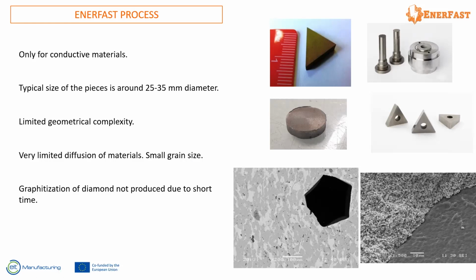And of course, there is no diffusion. The time is very short. It means that what you put in the die is what you will get after the end of the process. This is good for some materials and not so good for others. And also in the case of metal diamond tools, you can avoid graphitization of the diamond because the process is very short.